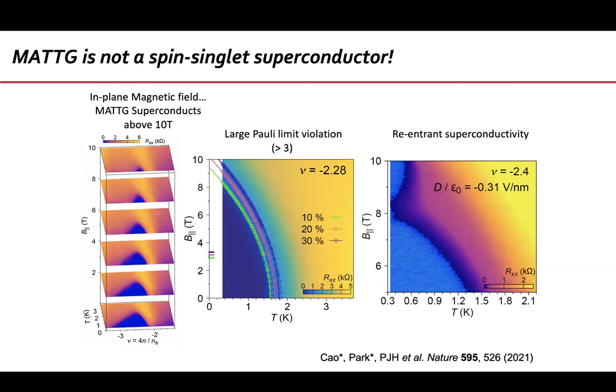This is all analyzed in this paper. And that's part of the reason why, for the bilayer, we don't see a big violation of the Pauli limit: this in-plane orbital effect is very big. For the trilayer, because it's mirror symmetric, the effect from the in-plane field cancels between the bottom two and the top two layers, and that's why you violate the limit by a lot. We thought the four layers, which is not mirror symmetric, would be like two, but the local top three layers and the local bottom three layers do have that symmetry, so you can calculate it, and it mostly cancels, not completely. And then five layers is again zero. You can look at all of these details here.